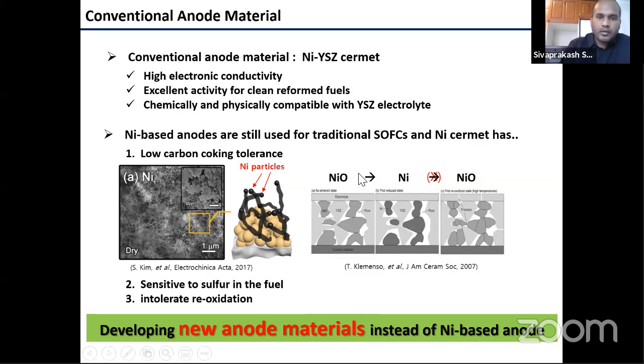The second disadvantage is that we start with nickel oxide as the electrode material in the nickel cermet anode, and once we start operating the fuel cell, nickel oxide is converted to metallic nickel.